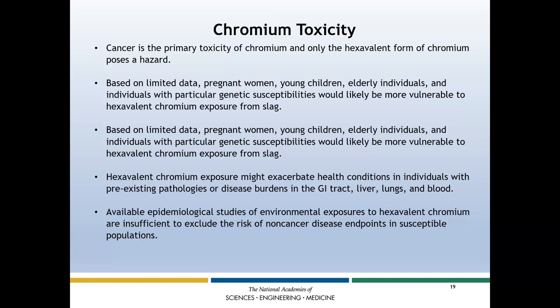But with chromium, the major concern is cancer, and it's really only the hexavalent form of chromium that poses a hazard. That may be a bit complicated to understand, but hexavalent chromium is basically chromic acid, whereas trivalent chromium is actually thought of as a nutrient supplement and not a hazard. Few studies have really addressed the extent of formation of hexavalent chromium in slag directly, but the available data suggests that the amount under ambient weathering conditions is relatively low.